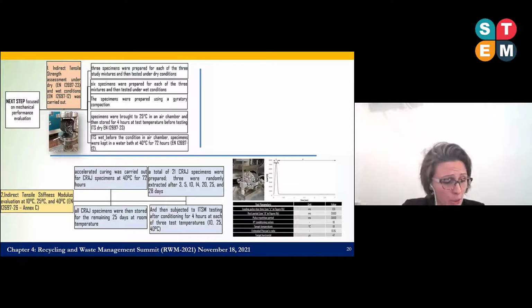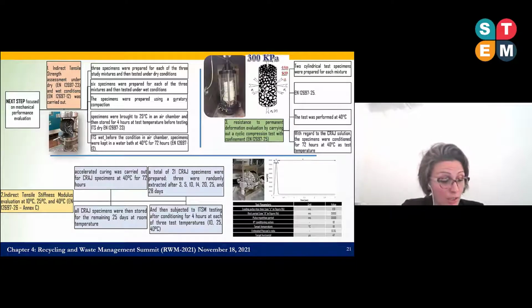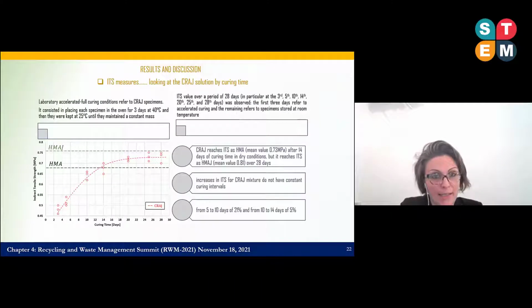In particular, we have to accelerate the curing process of the cold recycling mixtures at 40 Celsius degrees for 72 hours, because we need to reach the full curing of the specimen. Final step, focus on evaluation of resistance to permanent deformation. In particular, we have used a cyclic compression test with confinement on 2 specimens we prepared for each mixture. The test was carried out at 40 Celsius degrees. With regard to the cold recycling asphalt mixtures, the specimens were previously conditioned for 72 hours at test temperature.